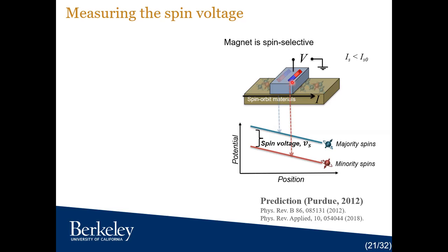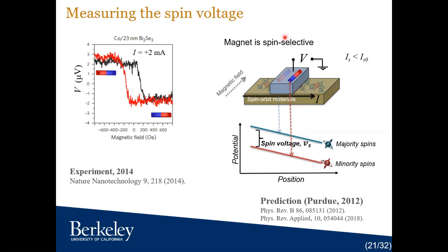And it was later demonstrated experimentally on a topological material called bismuth selenide around 2014. So in this experiment, they are measuring the voltage for a given current, and the current is around 2 milliampere. This current is fixed. All they're doing is applying an external magnetic field and switching this magnet. And for the two different magnetic states, they observe two different voltages, which correspond to this blue and red curve. And the difference between them is called the spin voltage.